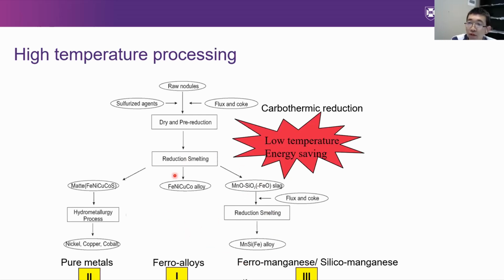So this flow sheet is actually designed to fit or use the current well-established copper smelting process or laterite processing route. First, the raw nodules are ground to powder, and then we add the flux to control the liquidus temperature, actually the melting point of the slag, and then adjust the coke to selectively reduce the metals. And after drying and pelletizing, it goes to a high temperature for the smelting and separation between the slag and the alloys.